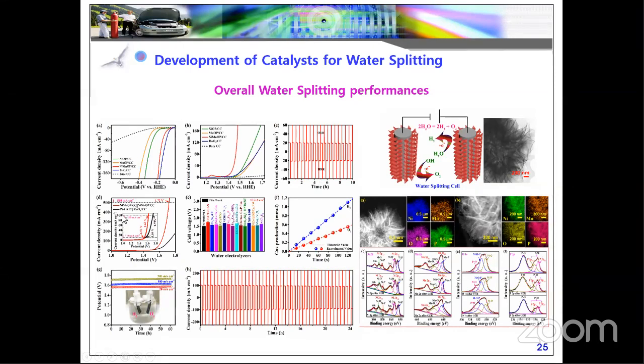And the overall water splitting, based on these bifunctional activities, our catalysts have shown a potential of 1.51 volt. But for the commercial catalysts, especially ruthenium oxide and platinum, the couple is that ruthenium oxide is the OER and the platinum carbon is the HER catalyst. Then we mixed them to make a device, and finally we got the performance. From the study, we conclude our material outperforms the commercially available catalyst.